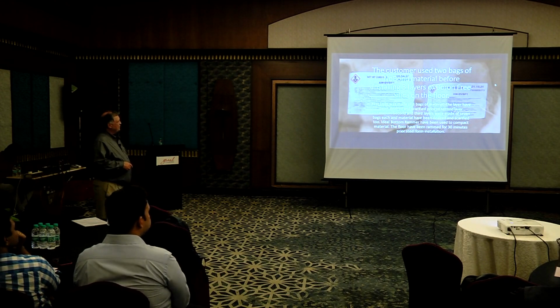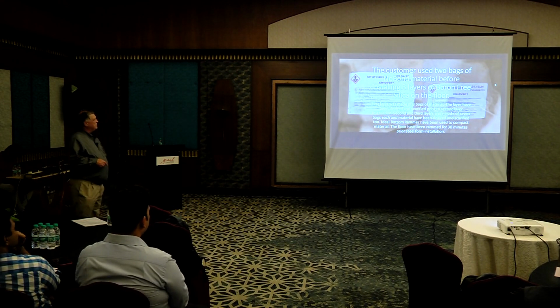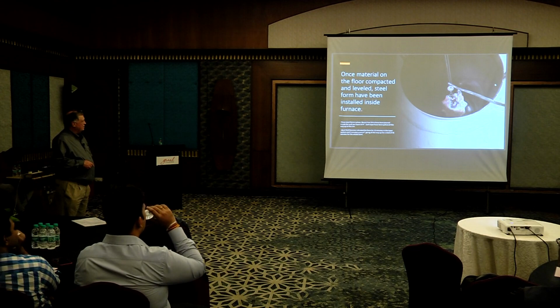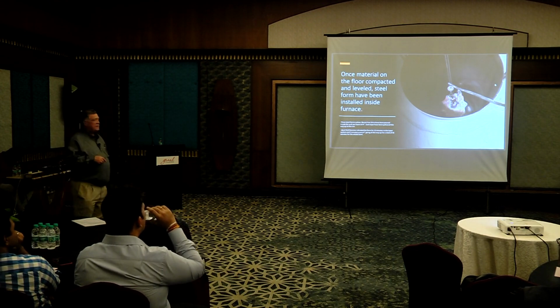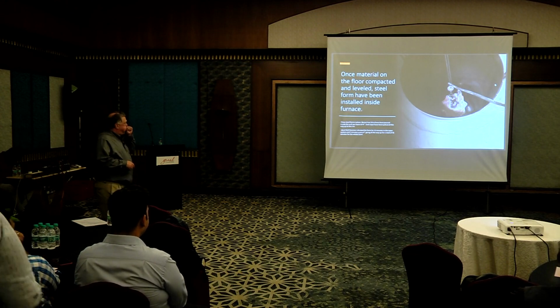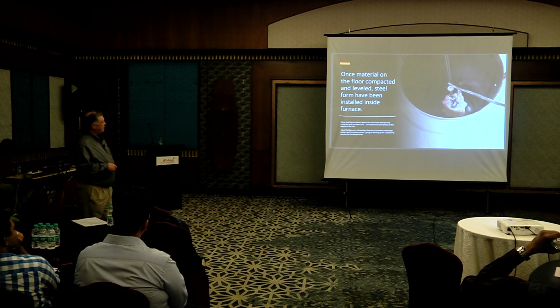So now they're going to the 9-ton furnace. The customer used 2 bags of no bond material before installing the floor. And again, they use the exact same thing. They're going to use the jolter. And we did use Defender on this form again, just to let you know. So the ideal rammer vibrated the form for 15 minutes in the taper, and 2 minutes every 4 inches, going all the way up the wall.